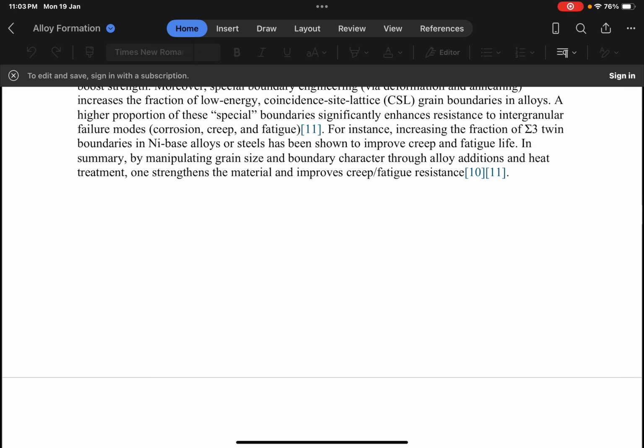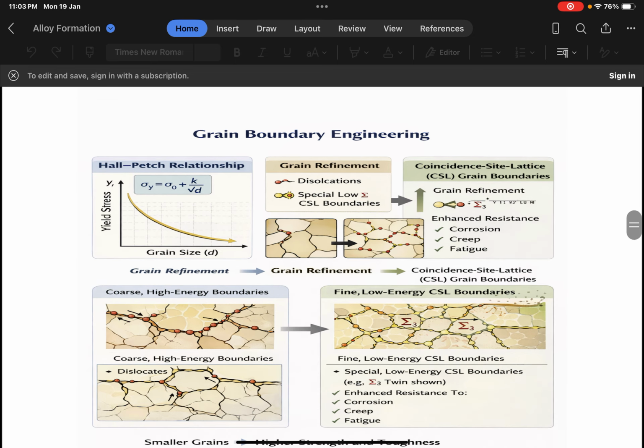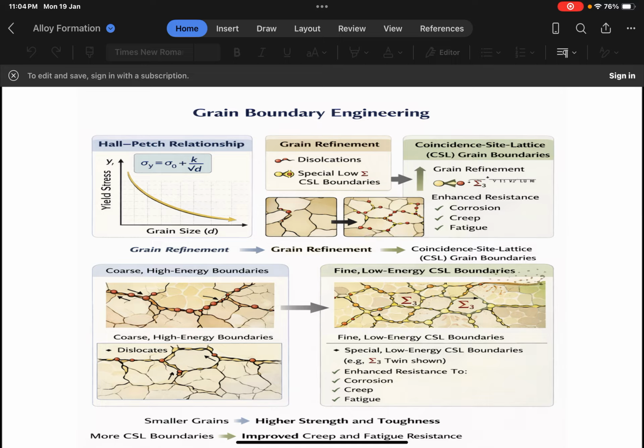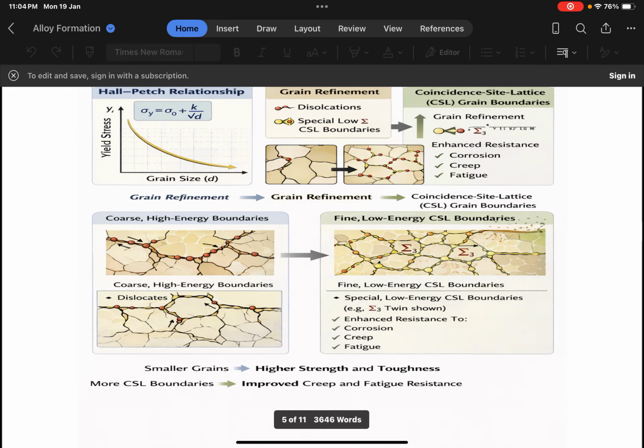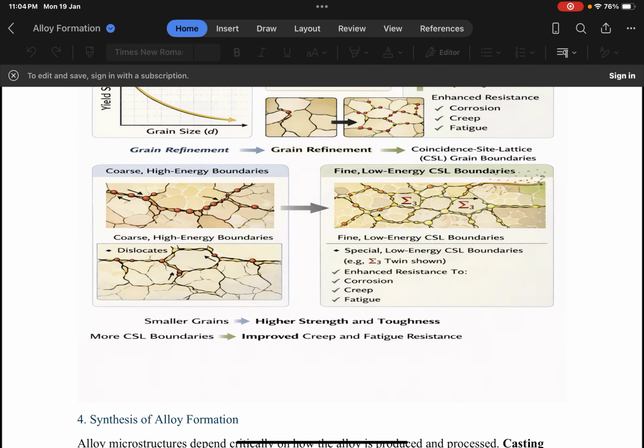improves creep fatigue resistance. As you can see on this diagram, grain boundary engineering, the Hall-Petch relationship, shows the variation of grain size with the yield strength in the first diagram, then grain refinement and coincidence site lattice, CSL, grain boundaries. Grain refinement is linked with the coincidence site lattice CSL grain boundaries. As you can see, smaller grain size means higher strength and toughness. More CSL boundaries means improved creep and fatigue resistance.